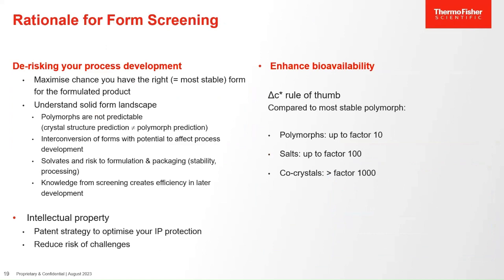Let me talk a little bit more about solid form screening. So Stephen also already mentioned some reasons for doing solid form screening earlier on in the presentation. First and foremost, solid form screening is there to de-risk your process development. In an ideal world, you would like to have the most stable polymorph for your formulation, for the very simple reason that if you have the most stable polymorph, there is no risk of this form converting to something more stable with less favorable properties that may not have the bioavailability that you need for your drug product. However, polymorphs are not predictable, so you have to do experimental work, and you have to compare the forms that you find to ensure that you identify the most stable of those that you find, and then you still don't have a guarantee that you have the most stable form, but a good chance that you will have found the most stable form.